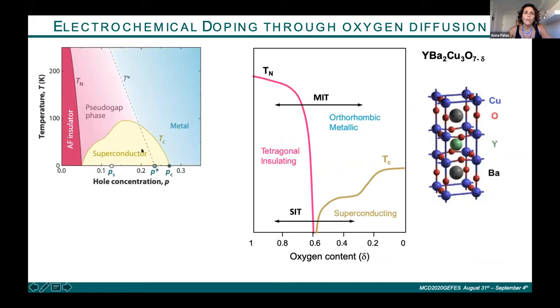Another possibility in order to drift the system from one state to the other, besides the use of a pure electronic effect, is to use an electrochemical doping. In this case, if we modulate the oxygen content of the material, we are able to induce these transitions. This is the same phase diagram that you observe here with the hole concentration, but as a function of the oxygen content in the YBCO cell. This delta here gives us the amount of oxygen that the system lacks.